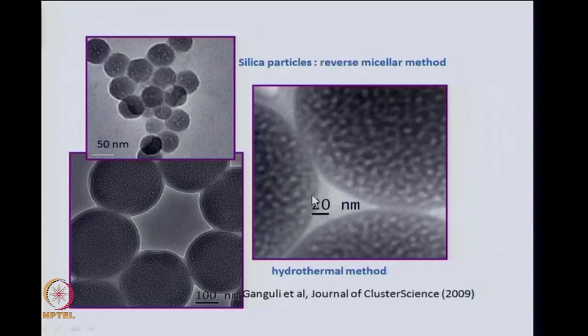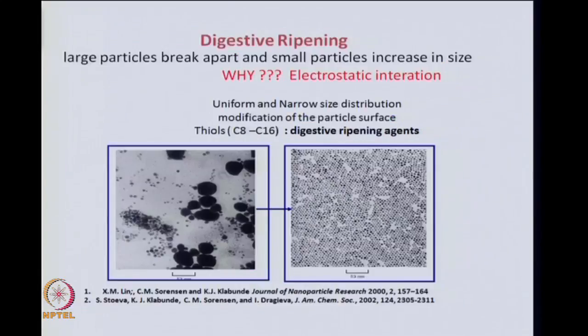And this we have also observed in many other systems, for example, in silica particles which we have made using micro emulsions. You can see these pores, and with time you can increase the size of these pores, and this is typically what you see in the last case as we discussed in TiO2, where Ostwald ripening will increase these pores and will lead to more dense outer structures.